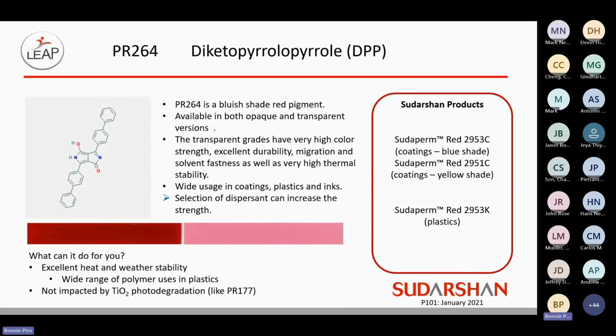From a formulation perspective, selection of the dispersant can really improve that strength area and really get additional value in that particular pigment. It does have a wide range of polymer suitability because of its high heat resistance and weatherability. This one is not impacted by TiO2, like the similar color space Pigment Red 177 that I spoke of earlier.